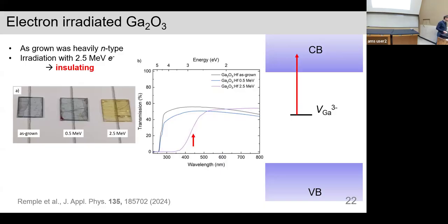But so where is this coming from? We think it's coming from a defect, a gallium vacancy, and an electron from that missing gallium point is being excited to the conduction band. And so there's a threshold in absorption. Notice the energy, which is proportional to 1 over the wavelength. Okay, so vacancies can result in color.